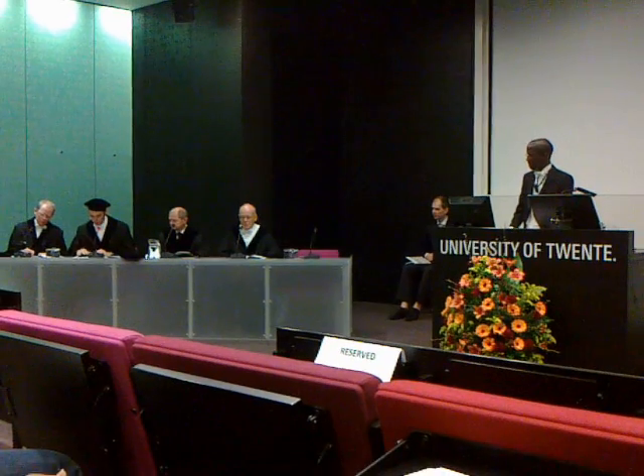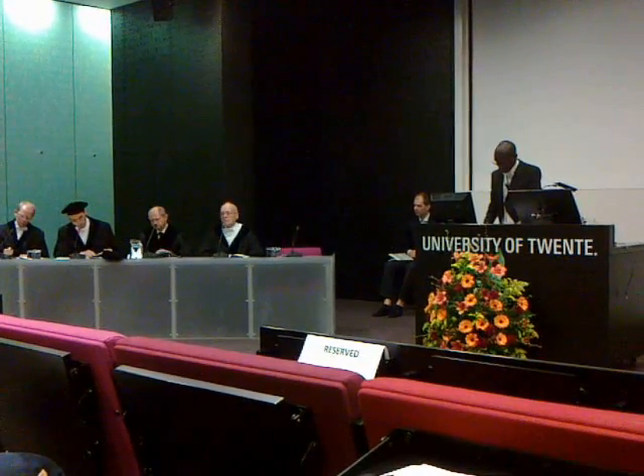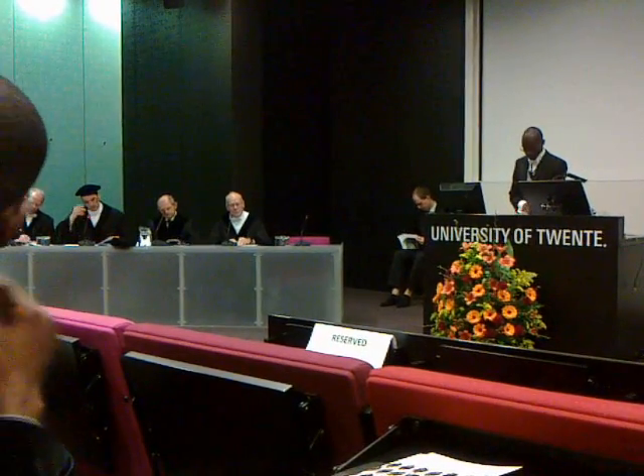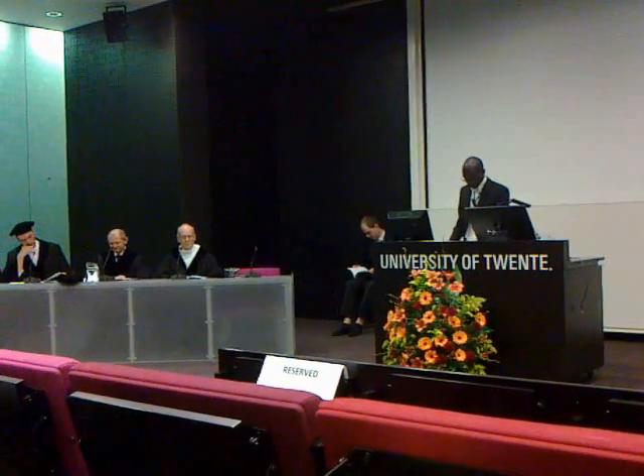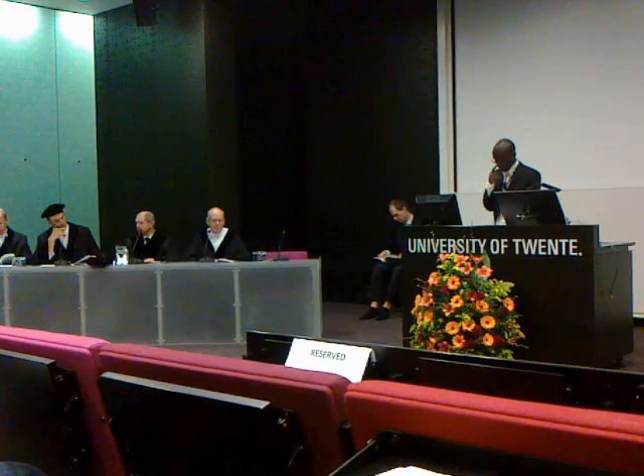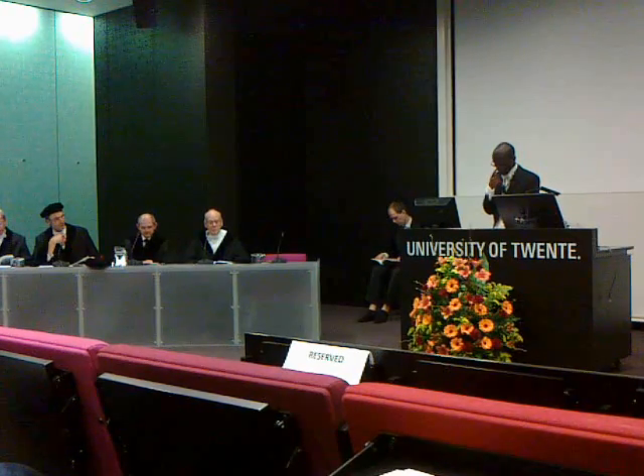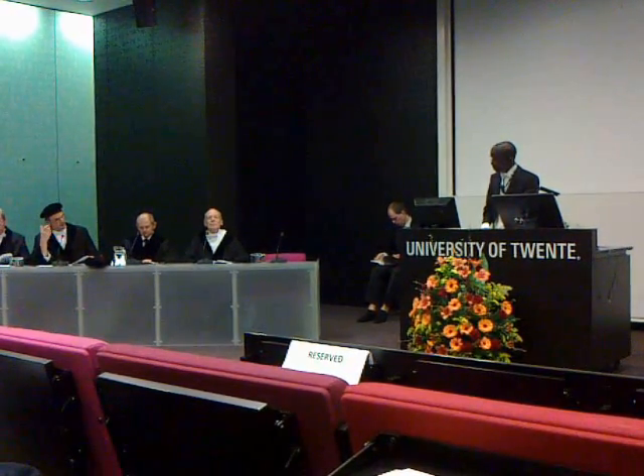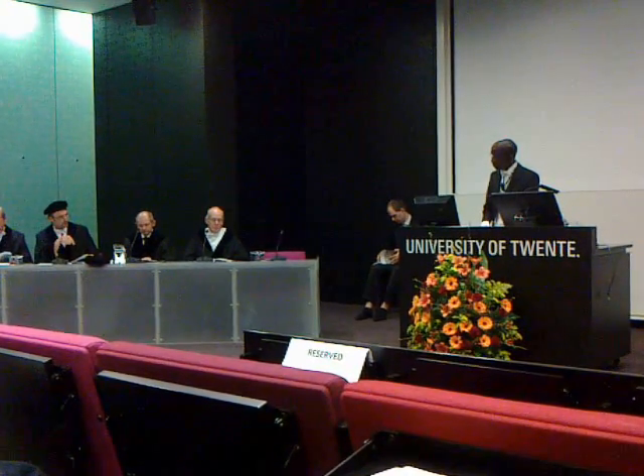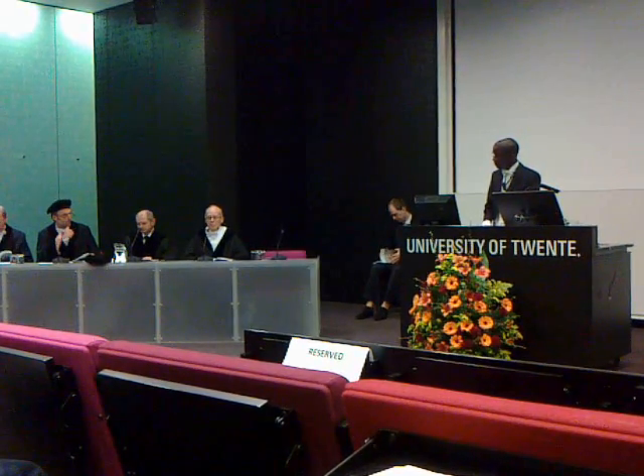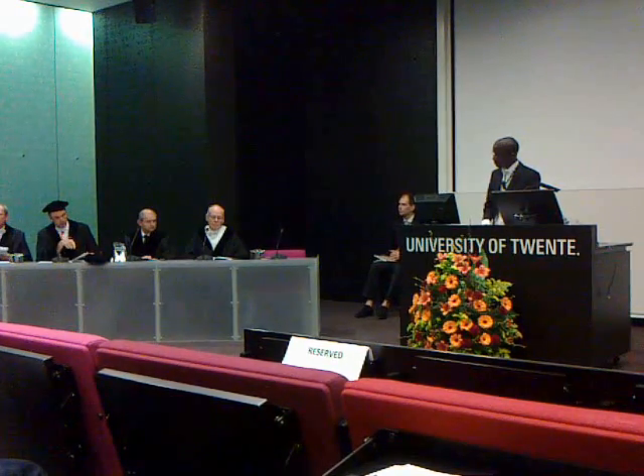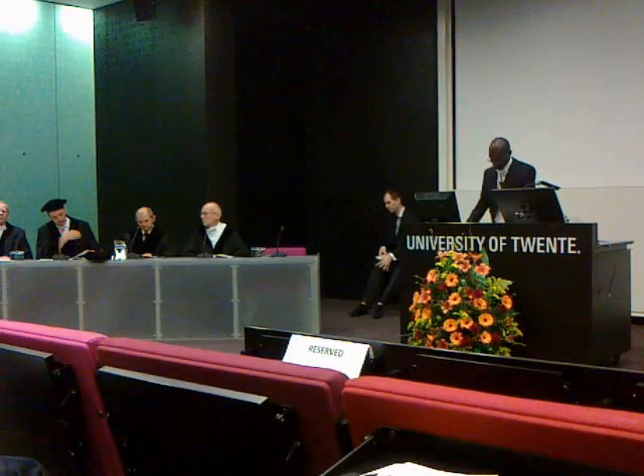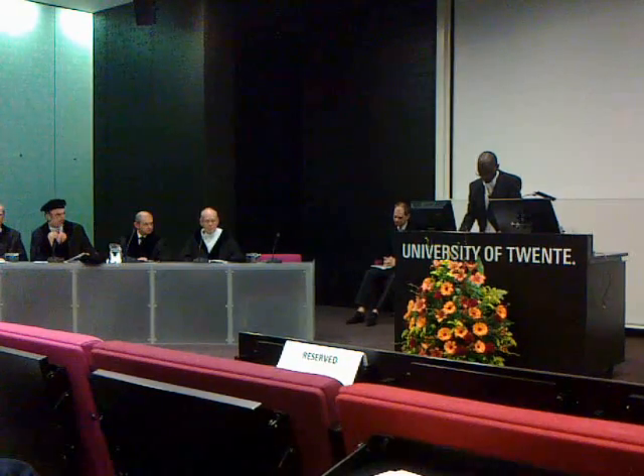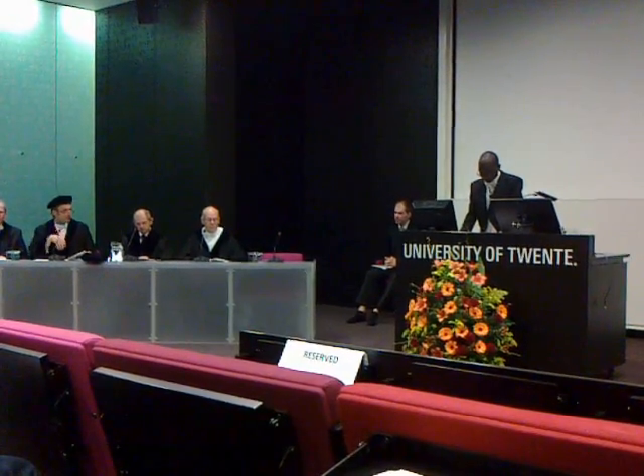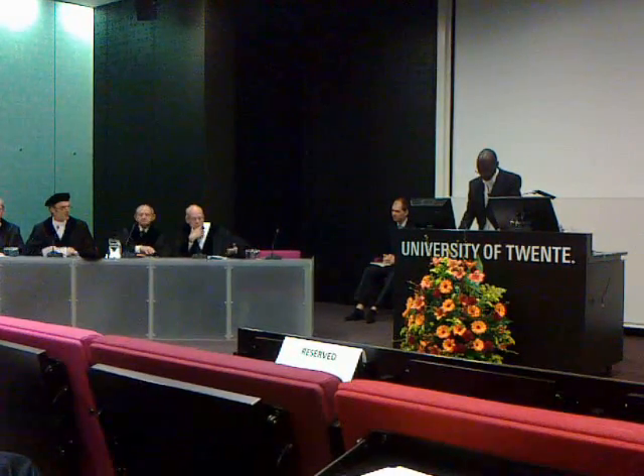Okay, perfect. Well, now let me move to the question that I have, and that deals with expression 1.15 on page 12. Yes. And I really don't understand this expression because it states that if you increase concentration, then the diffusion coefficient goes up. The diffusion constant becomes larger. Whereas I would say, but maybe this is very naive of me, if more neighboring sites are filled, that means that this prefactor 4 for a square lattice and 6 for a simple cubic lattice in 3 dimensions would go down. So what I would expect is just the other way around from what is shown in 1.15. I would expect that the diffusion coefficient would go down. But that's the way I see it.